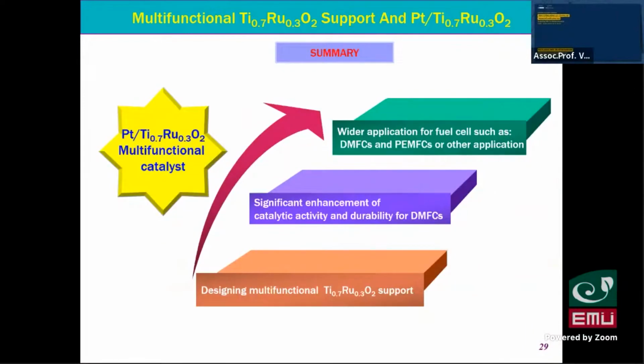So here's a summary for approach 2. We successfully synthesized Pt on titanium ruthenate oxide, and we can see this material as a multifunctional catalyst, because it not only functions as a support material for platinum, but also as a co-catalyst for platinum. It can release CO poisoning due to the ruthenium in this material, and creates a strong interaction between the ruthenium support and platinum.